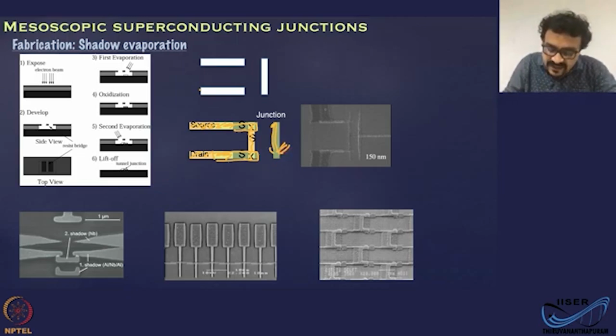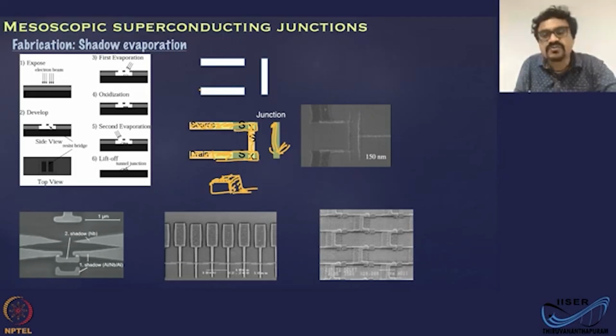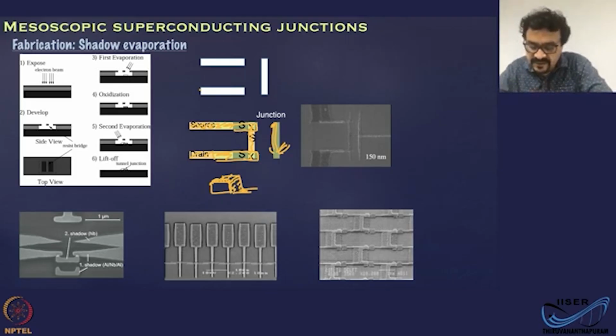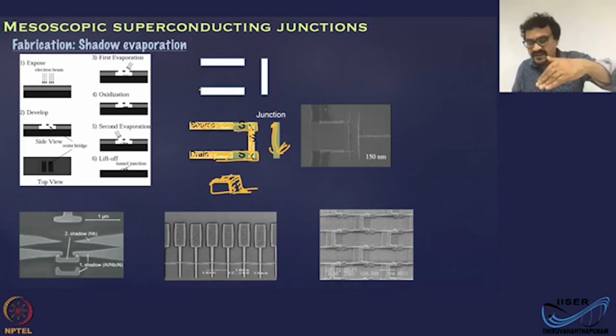But what you got is a superconductor which is oxidized. So there is a thin insulating layer in the middle. Then you get another superconductor that is a result of the second evaporation. So the first evaporation gave you this, then there is an oxide layer, the second evaporation gave you this, then you have superconductor, oxide, then superconductor. So there is a junction. This is an actual pattern where you can see two shadows there. That is why it's called a shadow evaporation, because you evaporate in one angle, oxidize, then you evaporate from the other angle, but there is an oxidation step in the middle.